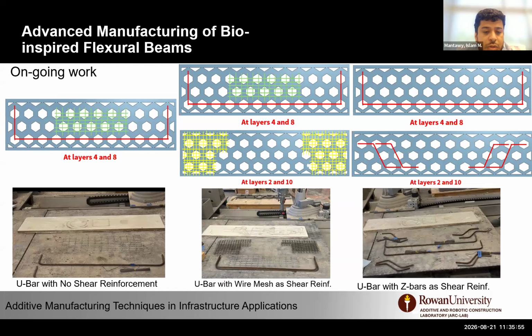So we take that in another direction when we start using bent bars. But in this case, we're using different types of reinforcement. So for the left beam here, you can see that we used a U-bar, but we didn't have any shear reinforcement. The idea intentionally was to see how this lattice structure can perform and what the shear capacity of this beam is. And after that, we came up with different reinforcement techniques where we tried bent bar, and we also tried using welded wire mesh in the shear region, and even distinct Z-bars, as you can see here.